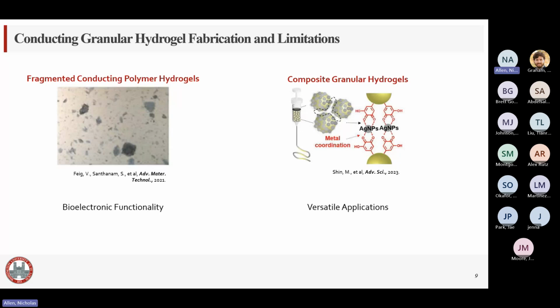However, you are incorporating the conducting components into a non-conducting hydrogel matrix. So the conductivity of these materials is typically much lower than the other method, as well as other conducting polymer hydrogel forms successful in bioelectronics. So they both have their pros, but they both have limitations that we still need to work to overcome in the field.